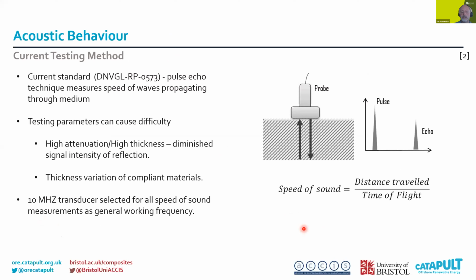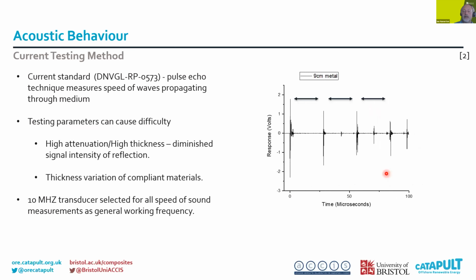So a probe is applied to the surface and a pulse is transmitted through the sample. It hits the back wall, it comes back as an echo, and you can see that as quite a simple test here, carried out at one frequency, typically 5 or 10 megahertz. And that distance enables us to calculate the speed of sound as simply the distance traveled over the time of flight. Now, this is nice and straightforward if you're talking about metallics.